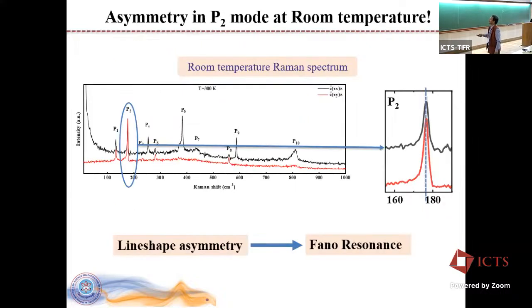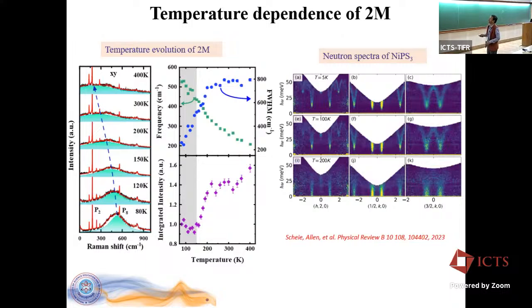Okay, so this he basically tried to understand with Fano asymmetry. Now, if you look at the spectra as a function of temperature, right around 80 K, the 2 magnon is somewhere close to about 600 wave number, and as we go to higher and higher temperature, you see how much it shifts. It goes almost to about 250 or 300 wave number. It's a large shift, and that is what is captured here.